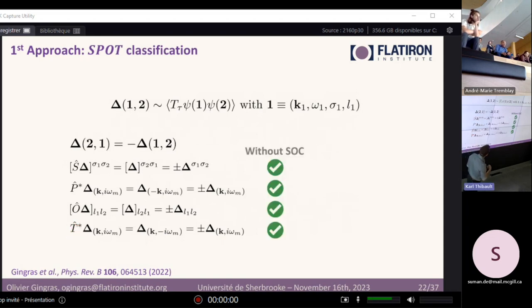So this is the case: they are decoupled without spin-orbit coupling. And so we can talk about pure parity representations. So even, odd, odd, for example, or something like that. But when we consider spin-orbit coupling, then some of these degrees of freedom, most of them actually, become coupled together and the description becomes much more complicated. This is one of the things that was highlighted in our work. So let's see some results.